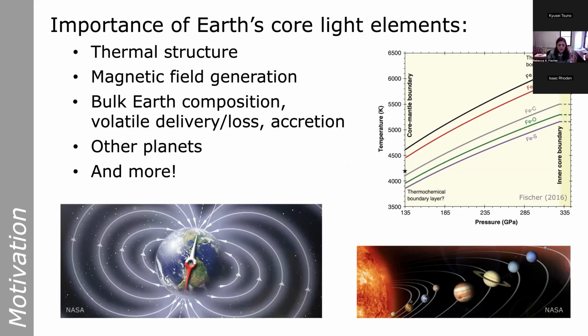And there's a wide variety of reasons why the light elements in the Earth's core are important. Just to give a few examples, they serve as a sort of thermometer. They tell us something about the thermal structure of the core. And that's because at the inner core boundary, where we have the solid inner core crystallizing out of the liquid outer core, the temperature should be near the liquidus temperature of the core alloy. The problem is that different light elements can significantly depress the melting point of pure iron by very different amounts. This probably outdated figure just shows some estimates of the eutectic melting point depression you get in each of these binary systems. Of course, it's more complicated in a more realistic multi-component system.